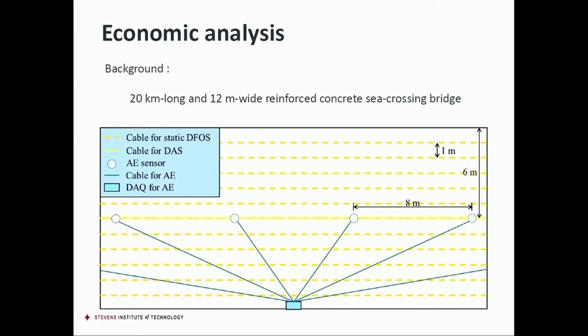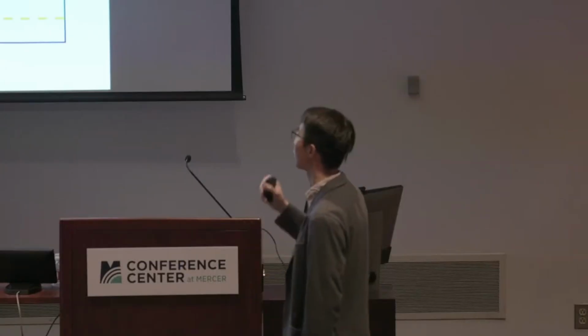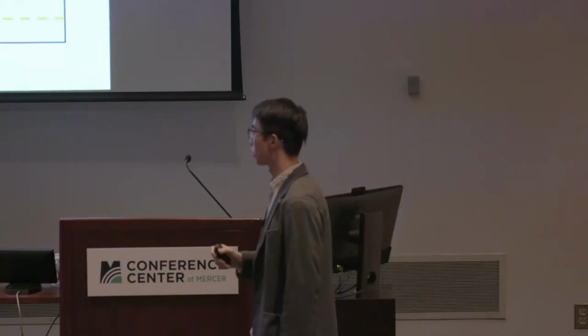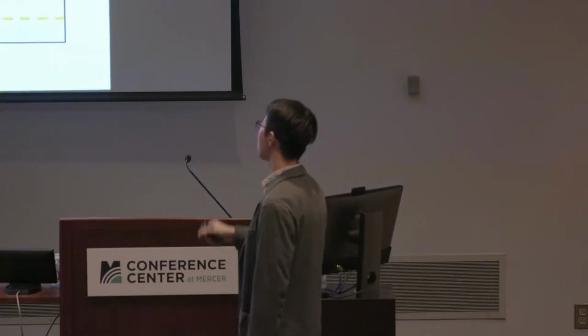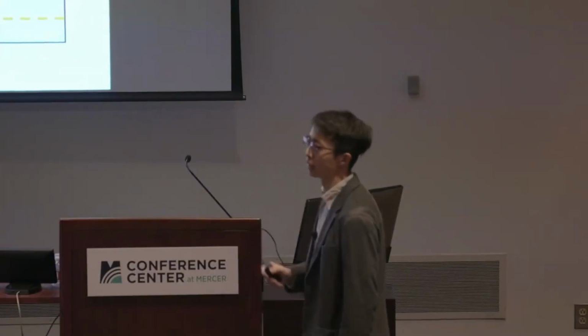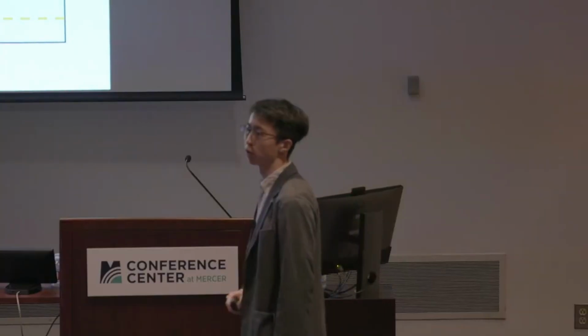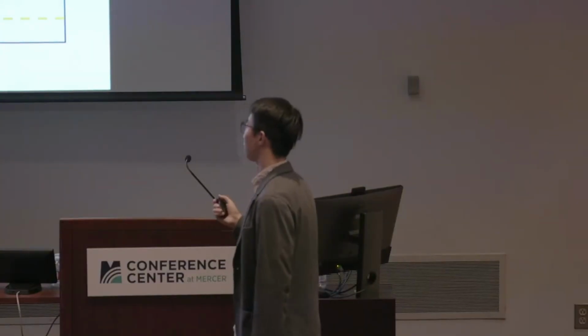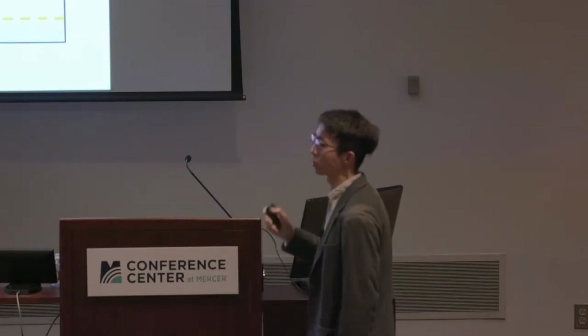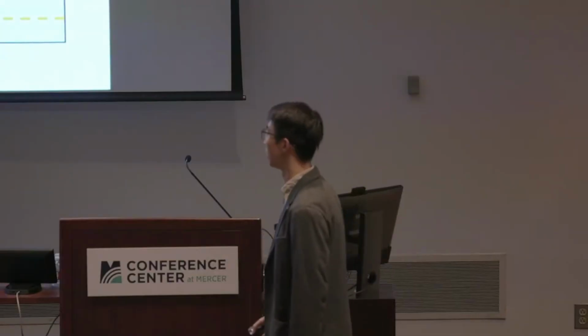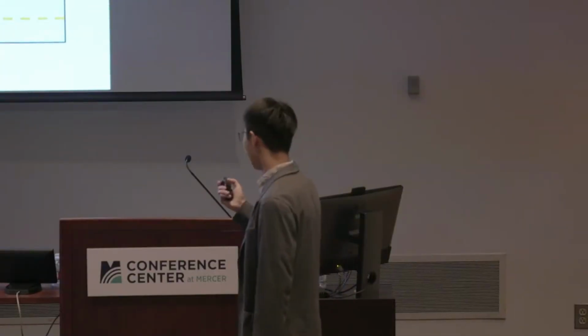And if we use static DFOS, as I said before, it just has a sensitivity of microstrain. It cannot achieve far-field monitoring. So you should install at least 11 fiber optic cables. However, if we use DAS, we can just use a single fiber optic cable and a data acquisition system.